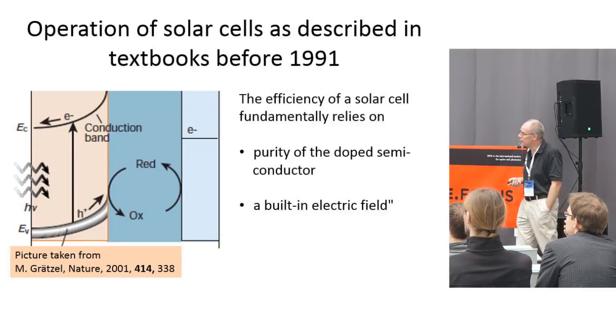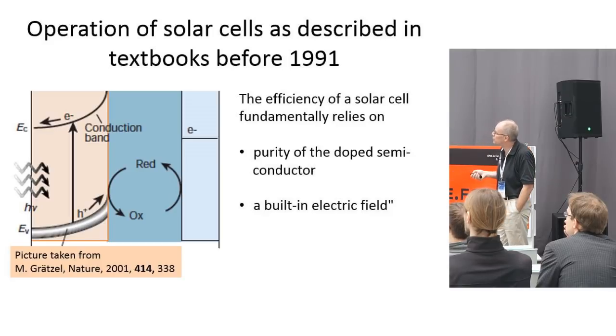A little bit on how we developed how this solar cell worked. This was the textbook before 1991, that you have a semiconductor in contact with an electrolyte. You form a Schottky junction, so you have a depletion layer at equilibrium, making an electric field in the semiconductor, and the band bending, as we call it. So when you excite the semiconductor, the electron goes in the electric field in this direction. The positive hole goes in the other direction and oxidizes the redox electrolyte. And for this to be efficient, the textbook said you need a very good quality semiconductor. Surfaces are a place where you have losses, recombination, so avoid surfaces and avoid defects and so on. And you need this electric field to separate the charge and to transport them.